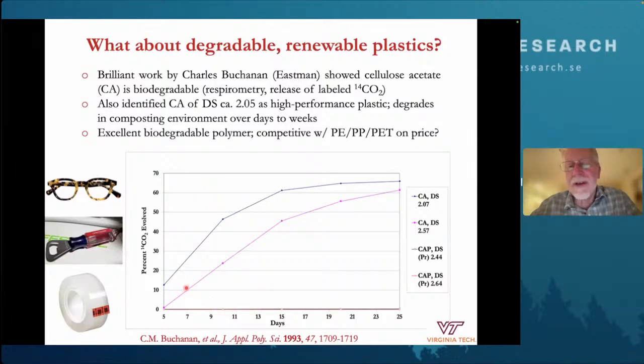But then you get up to DS 2.5 or so, which is roughly that same DS that's used for cigarette butts and for tool handles and eyeglass frames. Does biodegrade quite nicely over the course of about 3 weeks. And a lower DS, cellulose acetate 2.05 or so, biodegrades even faster. And he also identified that DS 2.05 material was an excellent plastic. It had excellent plastic properties, right? So there is a way to deal with this for certain plastic objects.